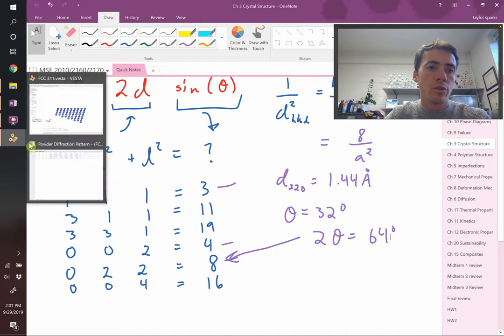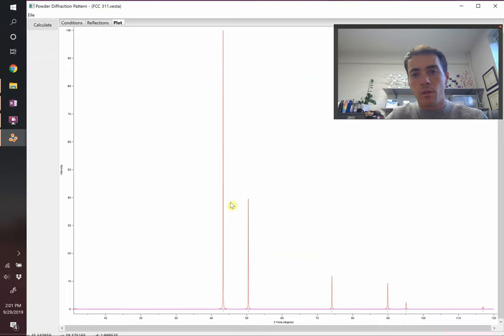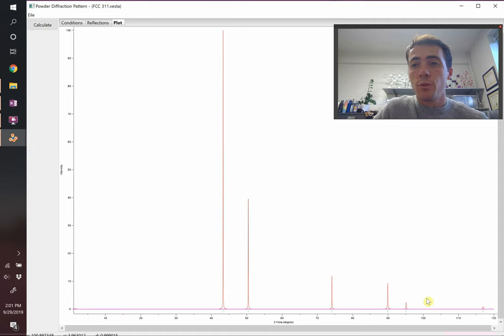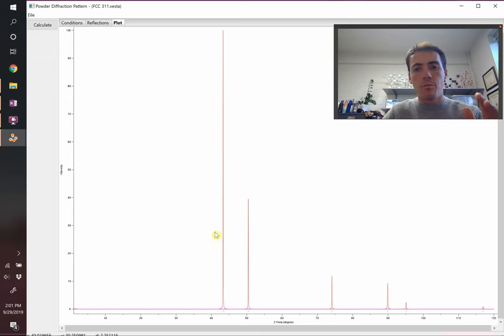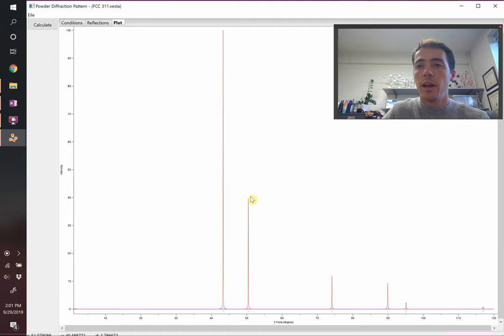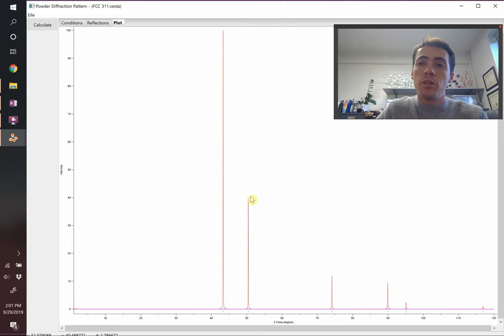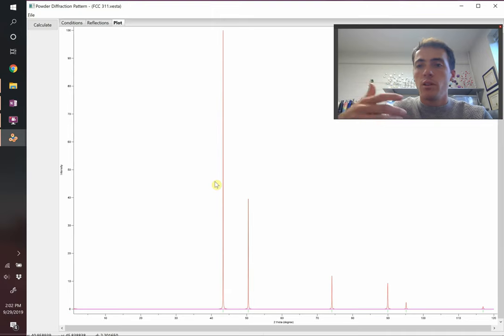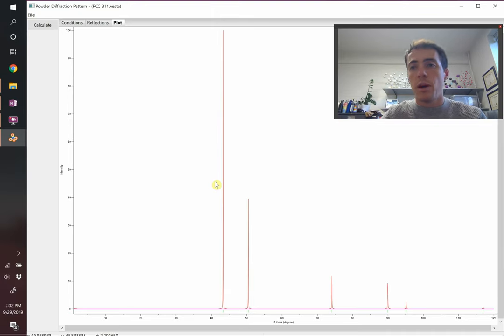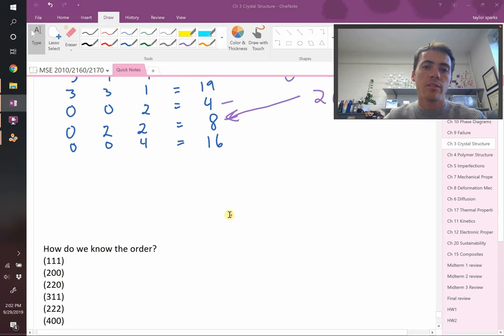In the real world, you measure a diffraction pattern on a machine and powerful search-and-match algorithms compare it to a library of known materials — matching peak positions and intensities — and identify the phase, saying for example 'this is likely aluminum.' You can even do quantitative mixture analysis: if a material has multiple phases, diffraction from all phases lets you back out percentages, like 26% alpha phase and 74% beta phase. That's x-ray diffraction — a super powerful tool.